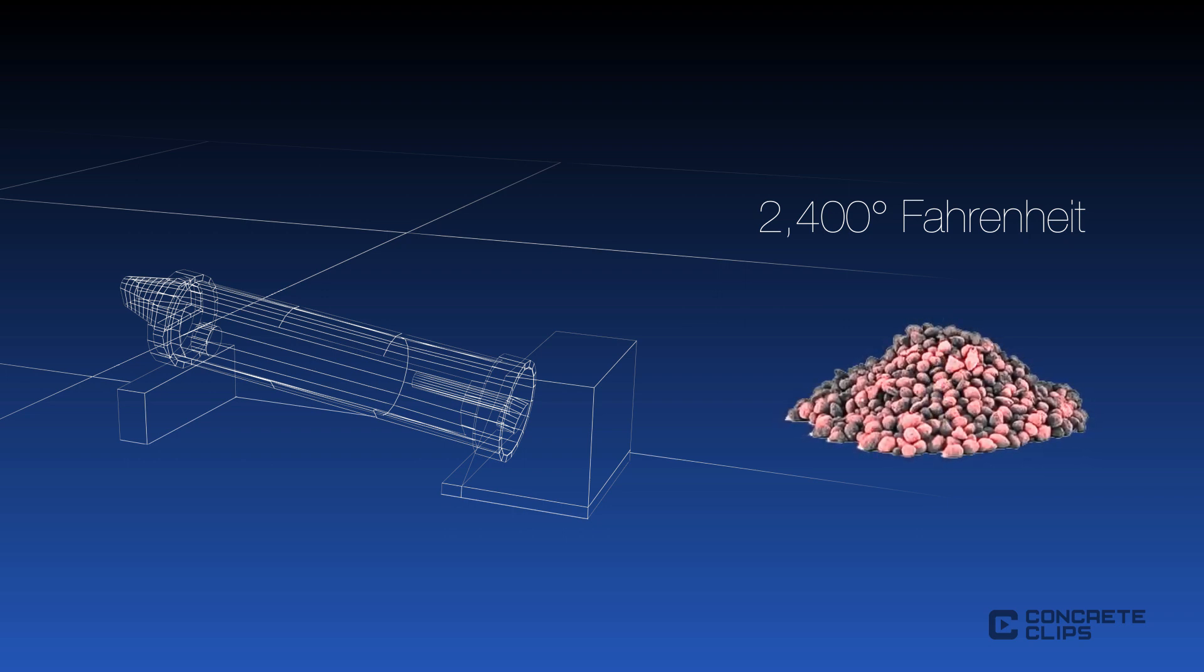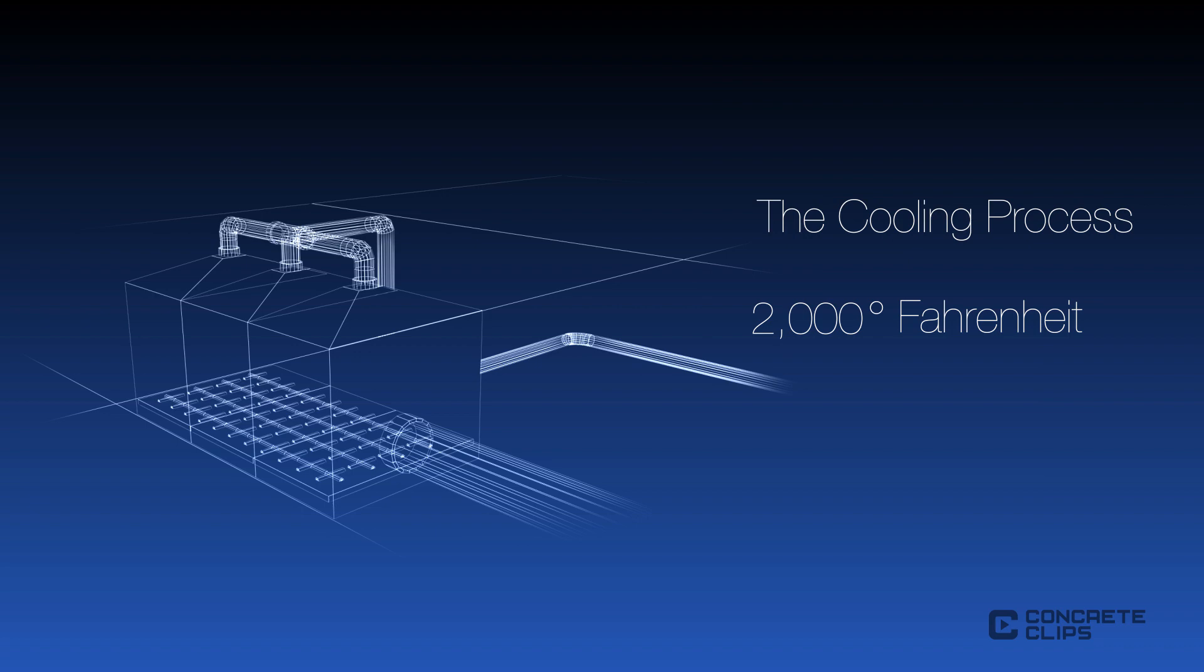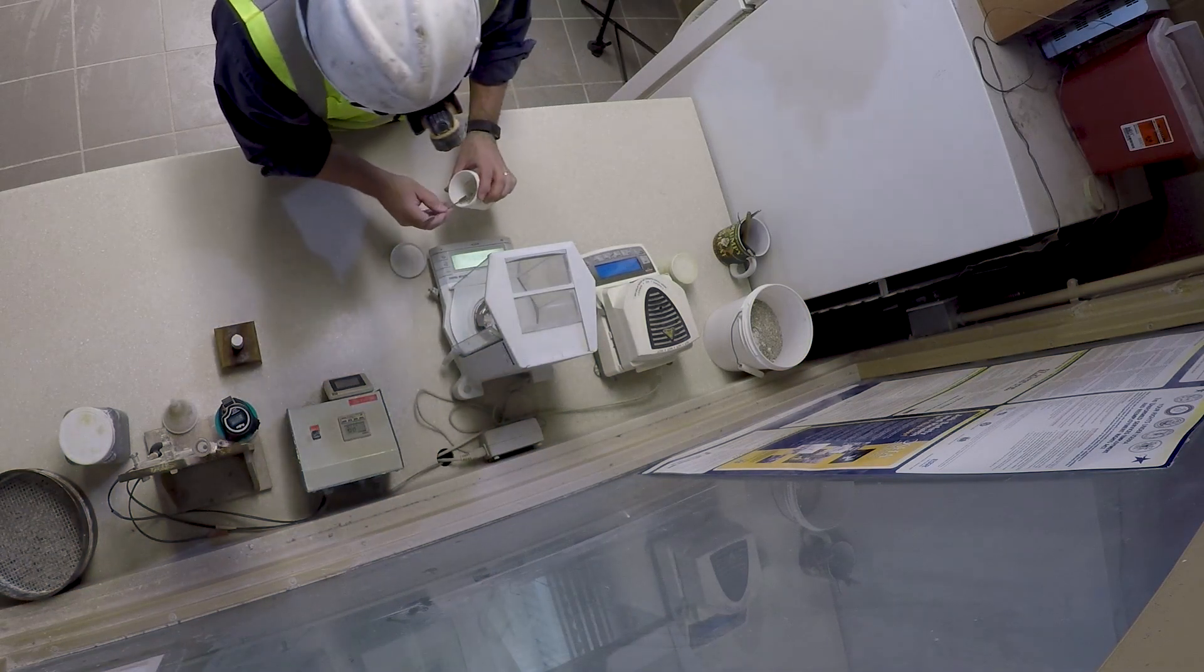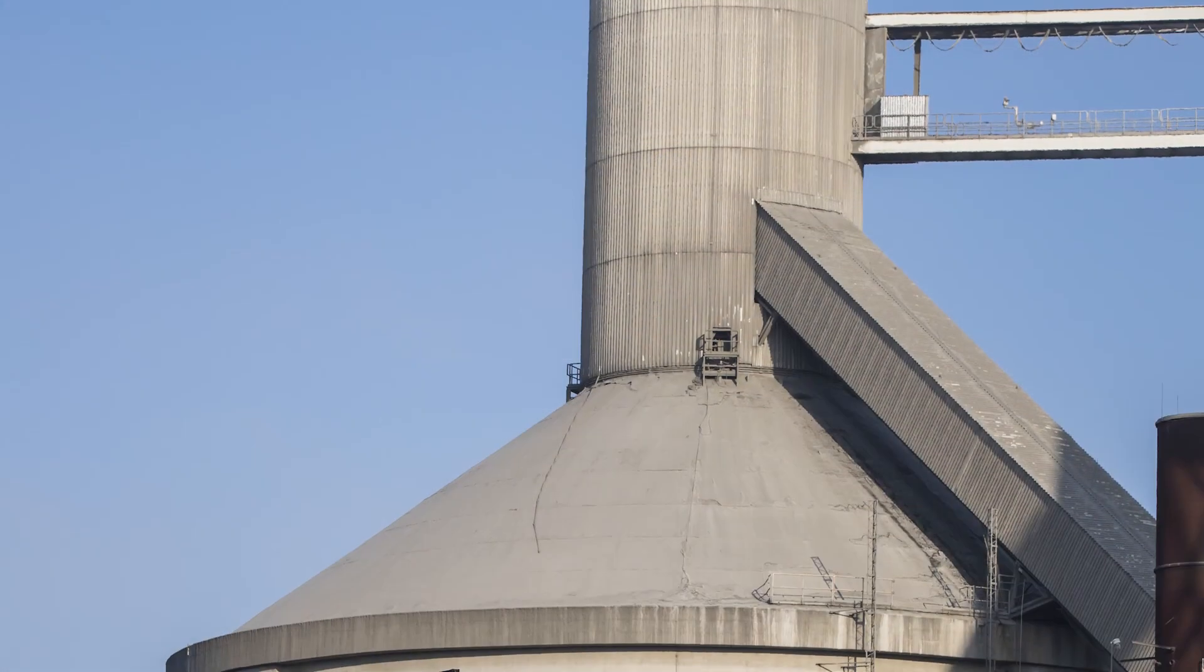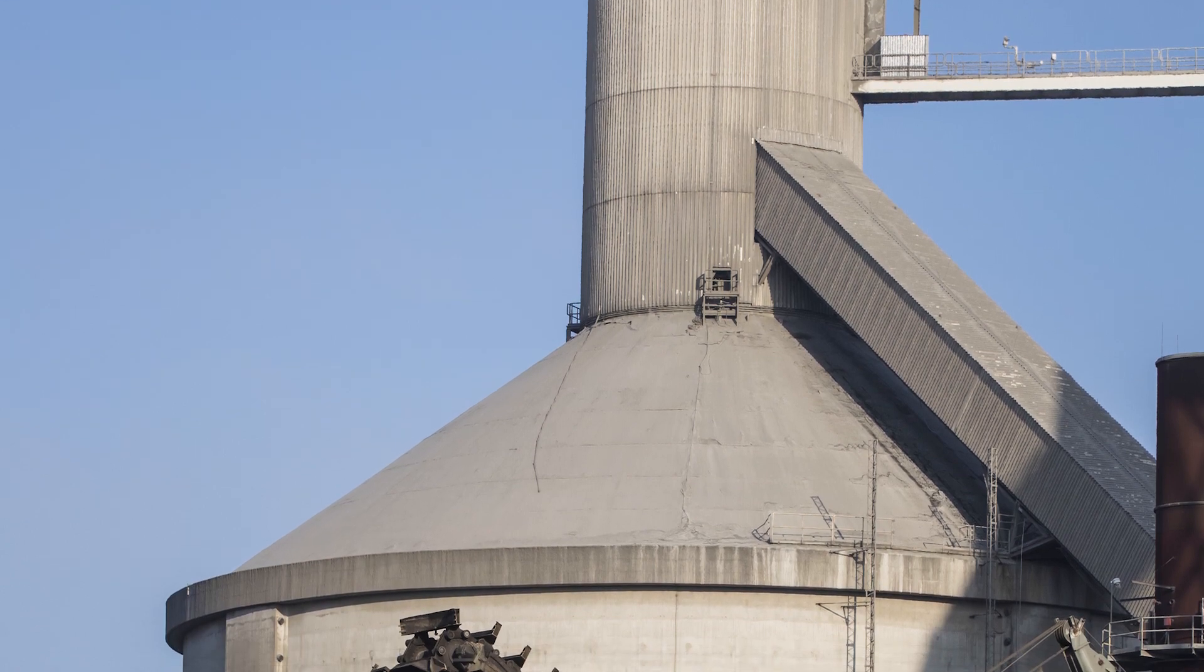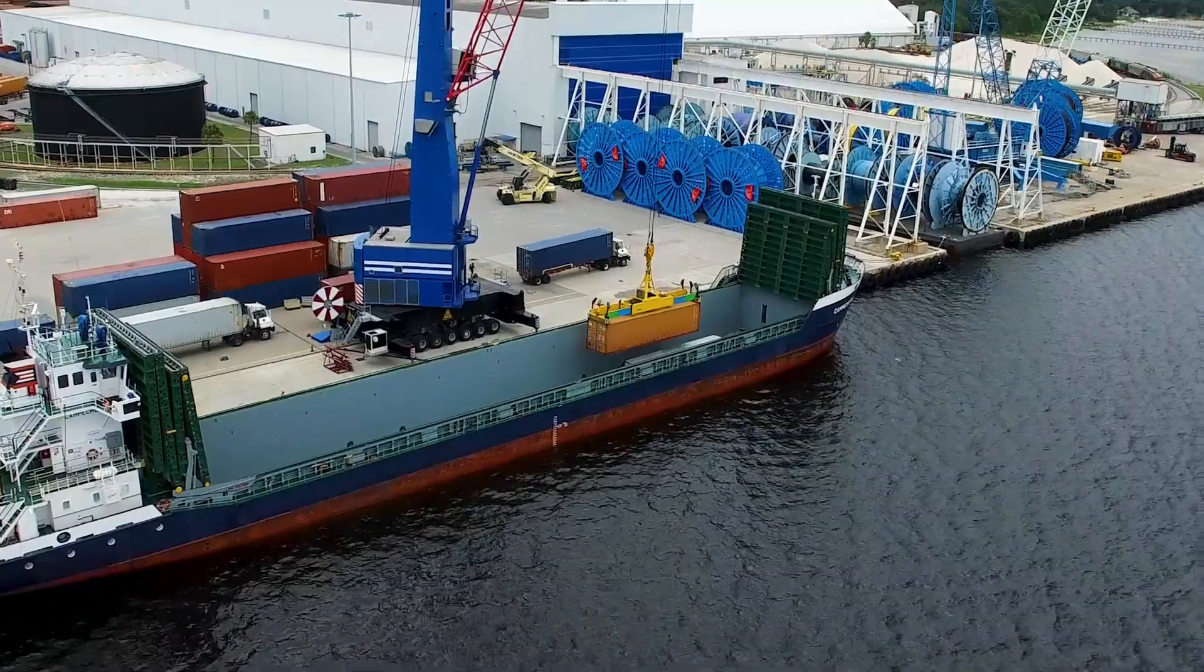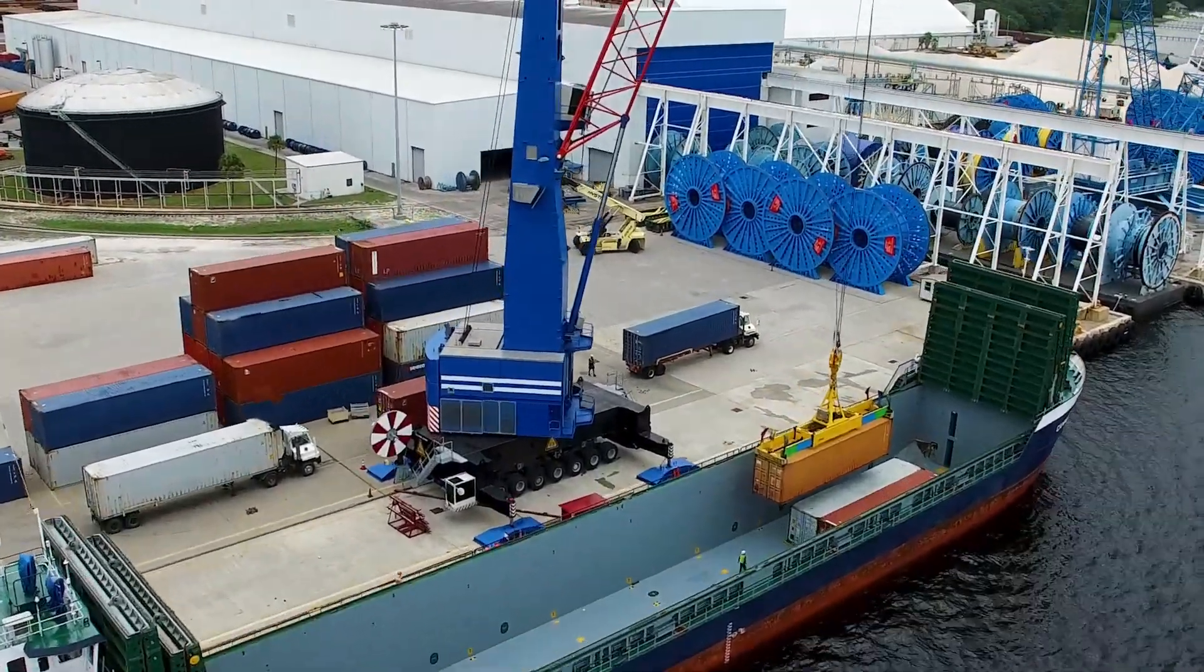The final step is the cooling process where the clinker is cooled and the heat is recovered and recycled. The clinker solidifies to form the two other components of Portland cement. The rate of cooling from 2,400 degrees Fahrenheit down to 2,000 degrees Fahrenheit affects the cement properties with rapid cooling resulting in a more reactive cement. Cooled clinker can be kept for several months without noticeable loss of quality if stored in dry conditions, making it amenable for shipping and trading in large quantities.